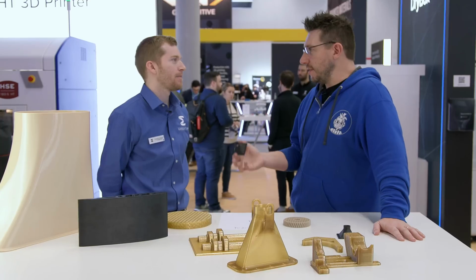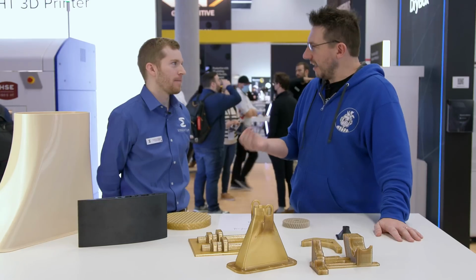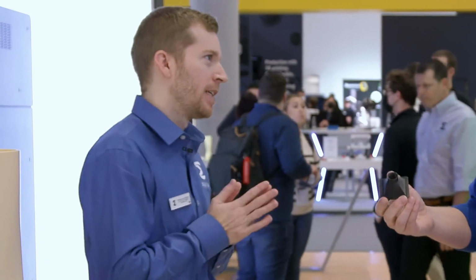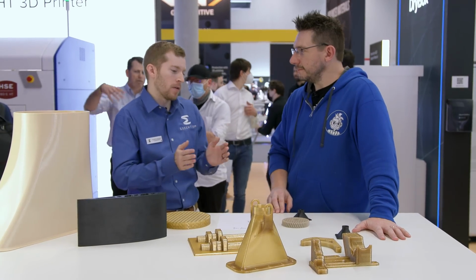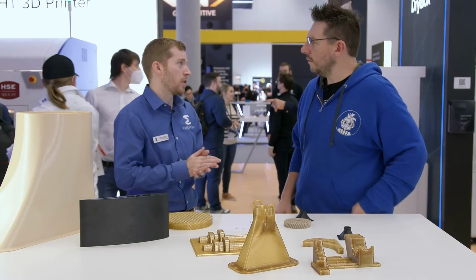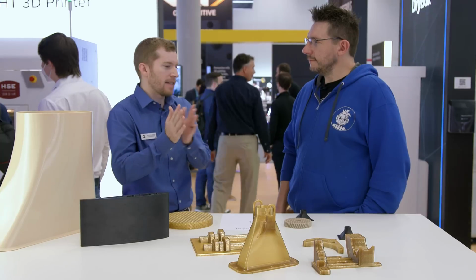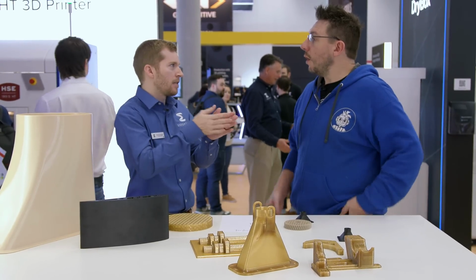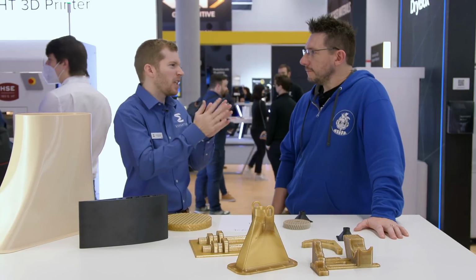Chemical resistance, though, meaning that with PLA, a lot of times chemical compounds could degrade the material. With PPS, that's just not the case, or is it just less? That's when we get into the chemistry. When we talk about chemical resistance, a lot of it has to do with whether it's semi-crystalline or amorphous. As a general rule, semi-crystalline materials have better chemical resistance because when those chains pack up like that, it's much harder for solvents to diffuse in and cause them to come apart. The chemical structure and that crystallinity really likes being a crystal.